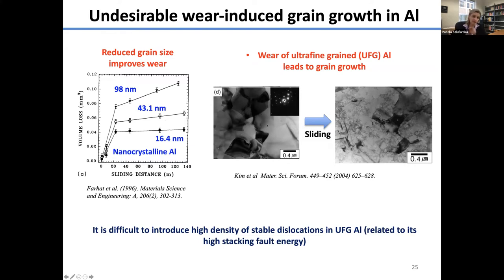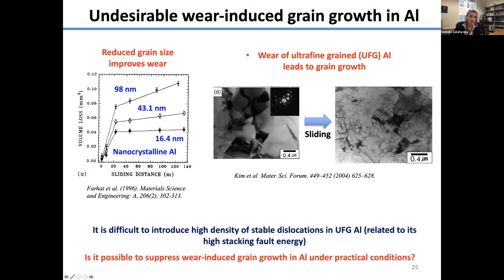So the grain size is smaller than a micron. You can see grain boundaries, and then after prolonged sliding, you can see the development of large grains with dislocations inside. It turns out that once we go to the micron regime or lower, in this ultra-fine grain regime, it is difficult to introduce dislocations into a material like aluminum, because of its high stacking fault energy, fast enough to continue this grain refinement. So we ask the question: since aluminum is so promising, is it possible to suppress grain growth and control the microstructure evolution during wear of aluminum?